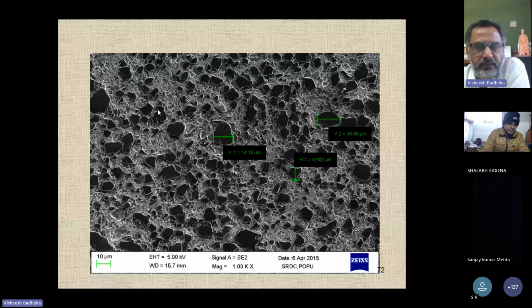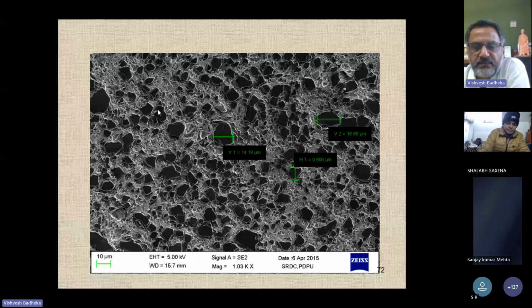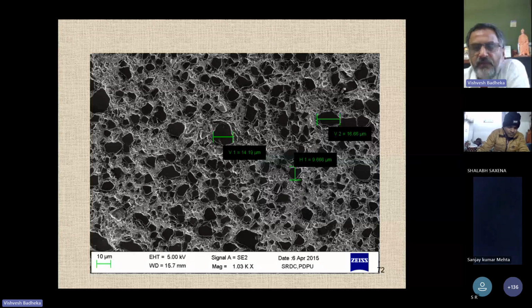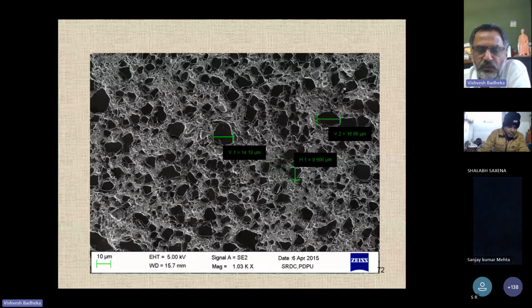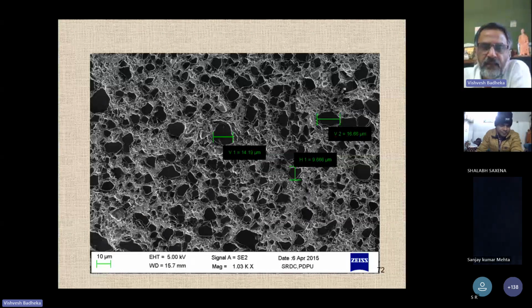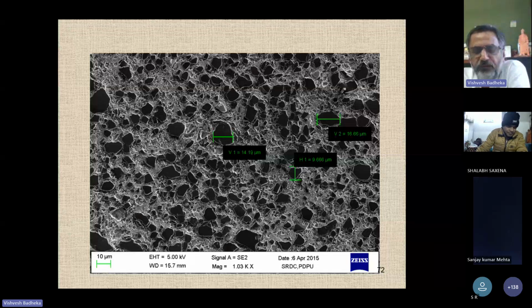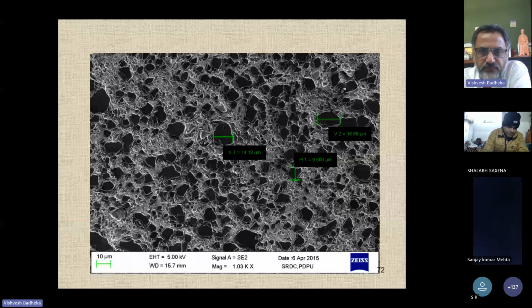At the same time, your aluminum matrix has a certain grain size, so the grain also gets refined further and further. So the final tribological property you are getting is a combination of the property of the matrix, I mean the refinement of the matrix, and the reinforcement particles which you have added. Those particles also get fragmented further, and the most important thing is uniform distribution. The powder particles should be uniformly distributed in the matrix. Then only will you get a better metal matrix composite through the FSP route.